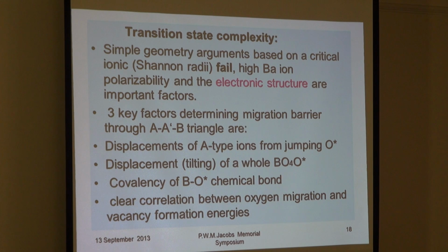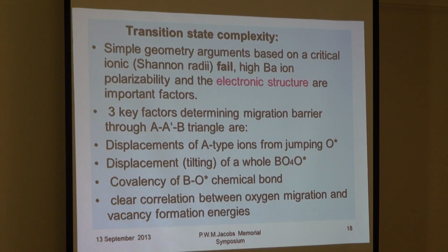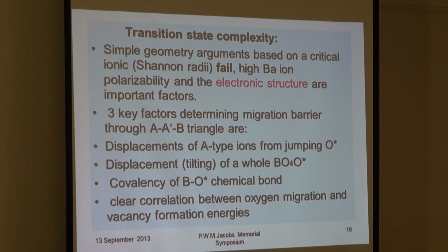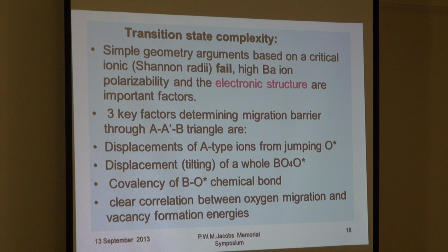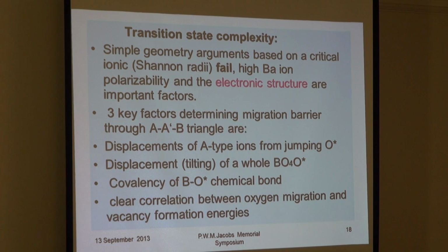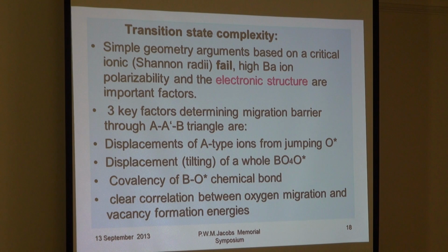But first of all, if you look at the standard analysis, people try to use ionic radii, so-called Shannon analysis. It's not really correct, because essentially there is considerable covalence in these materials, and it's not oxygen 2-; in these materials you find an effective charge of minus 1.5 or something like this. And also for B cations especially, there is considerable covalency and bonding between the B-type cation and oxygen. So first you should very carefully redefine what the ionic radii are in these materials, so we did.